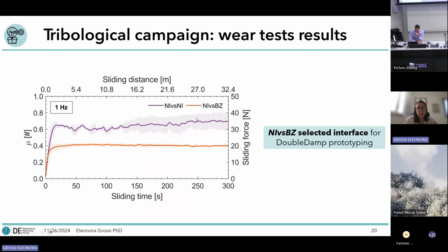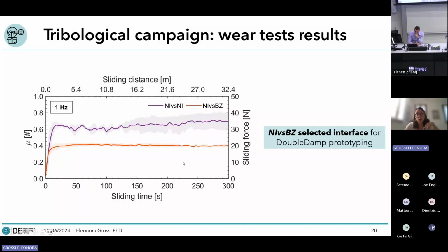You can see also that both lines have a colored area above them, which represents the standard deviation over 5 different tests. You can see that the nickel-bronze coupling has a smaller area, meaning that this coupling is more steady. And also you can see from this graph that it is quite a straight line. So I decided to use this coupling as an interface to prototype my device.